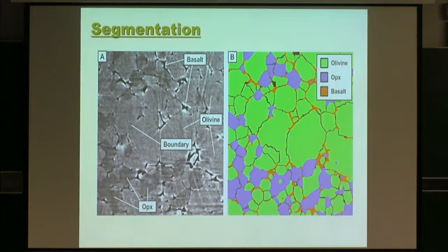But if the boundary is wet, right, at a melt percent that's higher than our resolution, then we can tell the grains and the grain boundary. So the melt can be easily told apart, the orange, right? And the olivine and the OPX, we can also tell, but if there's just an olivine to olivine dry boundary without melt film, then the boundary, you have to take with a grain of salt.